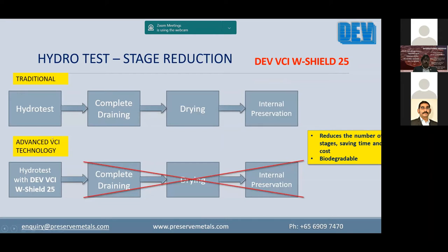So when compared to this set of activities, just by adding the VCI W-Shield 25, which is an advanced VCI solution, we will be able to completely eliminate these additional stages. Once the hydro test is done using this 2% additive solution, whatever the normal draining is done, we just close the ends of the piping and keep the system sealed.